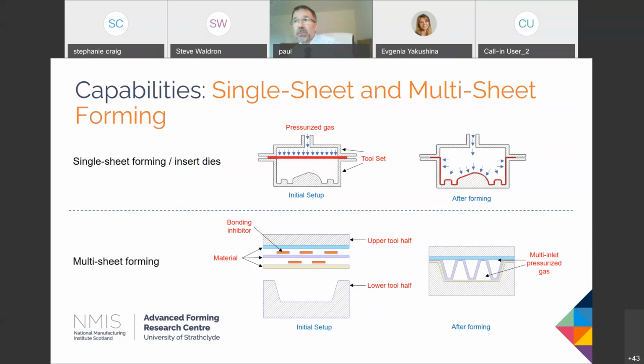So what we do is clean the sheets, apply the bonding inhibitor. We then take that pack, heat it up to a fairly high temperature under mechanical pressure, and we have this process called diffusion bonding. Titanium is unusual as a metal in as much as it dissolves its oxide film. By holding the pack at a high temperature under pressure, the material bond lines completely disappear. And if you do the process properly, you effectively end up with a monolithic piece of material.